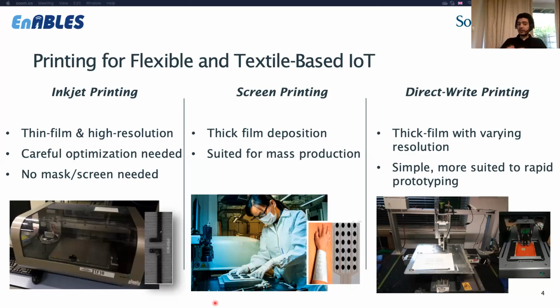us to print significantly thicker layers compared to inkjet printing. So one layer of conductive silver from screen printing can be in order of few micrometers as opposed to hundreds of nanometers. Ink layer very quickly and you get your complete system printed.